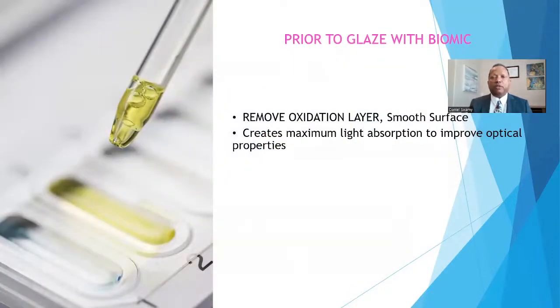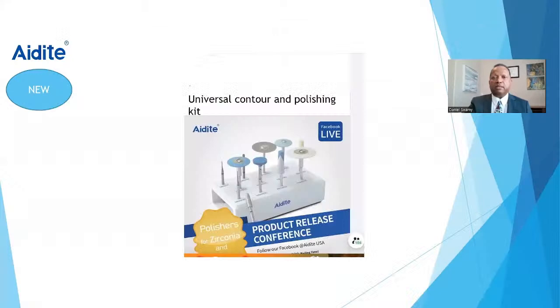One of the reasons you want to remove the oxidation layer prior to glaze is that you want the optical properties to be better than what it would be. So anytime you're sintering zirconia, you are actually forming an opaque layer on the surface of the restoration that forms a barrier to light absorption. Okay. So once this barrier is removed, then the light absorption becomes much better, and the optical characteristics get to be better when you apply the staining glaze or the Biomic coloration system. Aidite carries a whole range of materials for polishing and contouring.